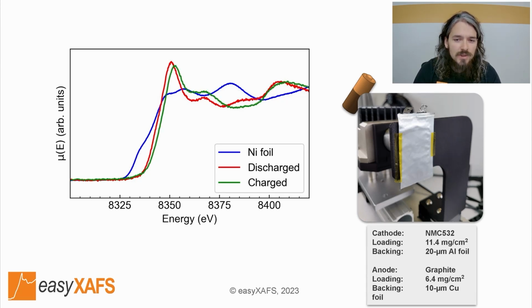The green trace shows the same measurement on the pouch cell after it has been fully charged. So it's clear that the energy position of the edge for the green trace is shifted towards higher energy, showing that the nickel atoms in the cathode were further oxidized during charging, showing that the nickel atoms participate in the charge compensation. This experiment can be repeated for intermediate charge states as well, and it is even possible to do operando to see smooth transition in oxidation state during charge and discharge.